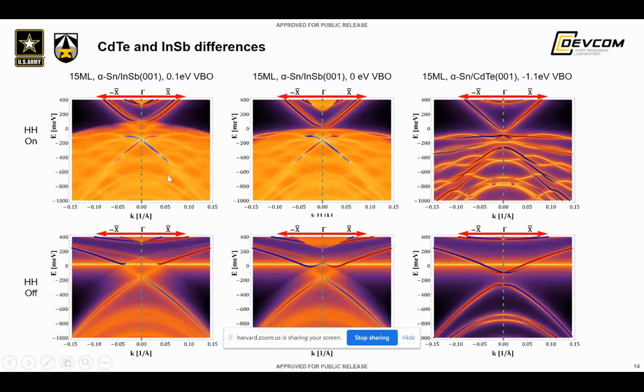These, again, remember, are theoretical simulations of ARPES data that can be expected. Shown here is a 15 monolayer plot of alpha tin on InSb, assuming a 0.1 eV valence band offset. You can see that even at this thickness you still get some distortion, but nevertheless, with or without turning off the heavy hole states, you can see that you get a formation of a Dirac cone at this thickness quite nicely in the InSb.